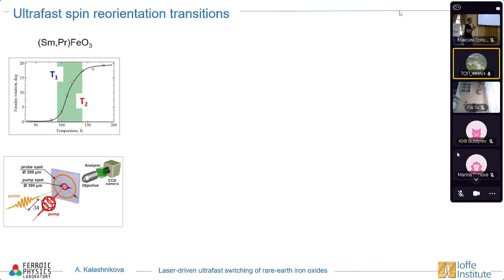Here it was somehow a little bit more complicated one. So basically, we used a single femtosecond laser pulse. We excited the material, which was in the low temperature phase. And then we used a delayed, very short probe pulse to get the magneto-optical image of our sample, basically to observe the orientation of magnetization at a particular time after the excitation. And we can take these images at different time delays.